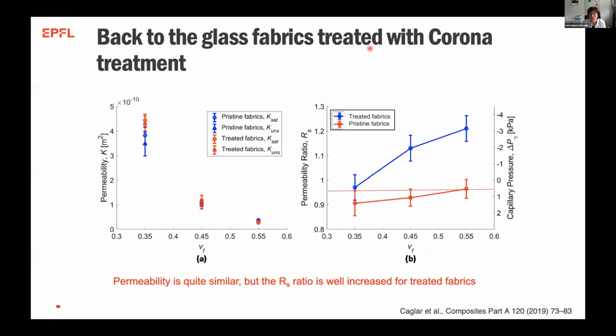I see, if we go back to the glass fabrics that we treated with the corona treatment that I presented before, we did measurements of permeability on the pristine and treated fabrics. And you see that, okay, the permeability, it was a saturated permeability.